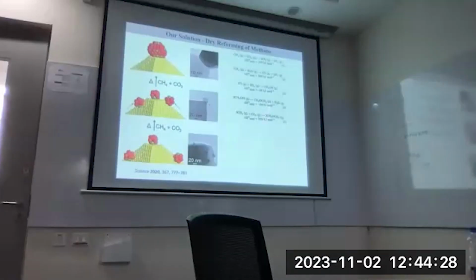Here, this is a highly endothermic process, but you get syngas, highly reactive carbon monoxide and highly reactive hydrogen. We use a magnesium oxide support, which is made in a different fashion, and a nickel molybdenum nanoparticle. Before we start using the catalyst, we first treat it with the reaction gas.